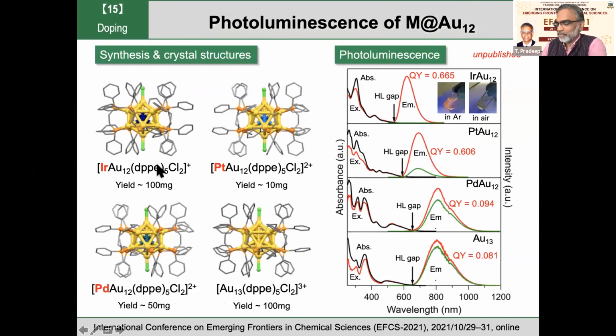Yeah, basically there are many methods we apply. The most simple one is co-reduction. And as you know, some of the clusters contain two dopants, some of them do not. So we have to purify them after that. But in some cases, we can use the hydride doping method. So in that case, we can start with the palladium or platinum centered gold cluster. Then we can fully convert this cluster into the doped cluster. So the yield is very high in such cases. A 100 milligram scale in a pure form is easily achieved by using the hydride doping approach. But in some cases, we have to use a conventional co-reduction method.